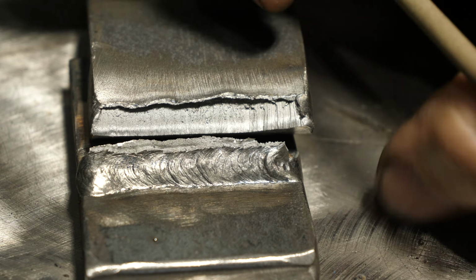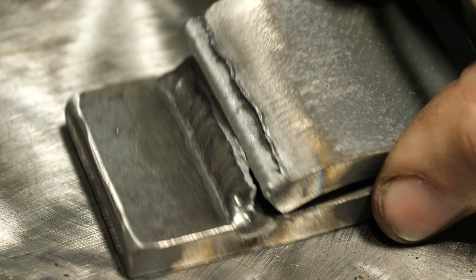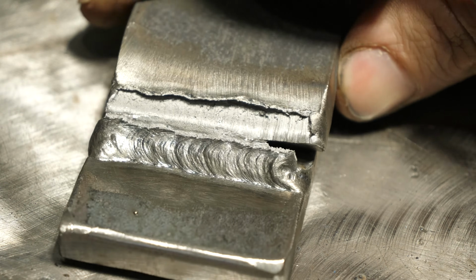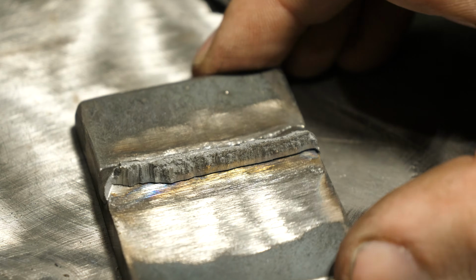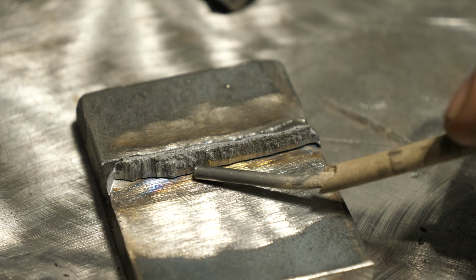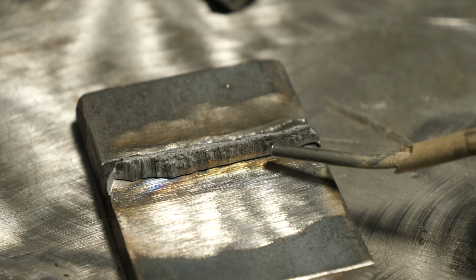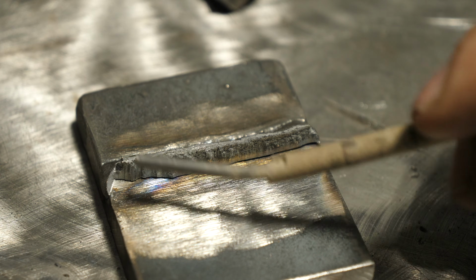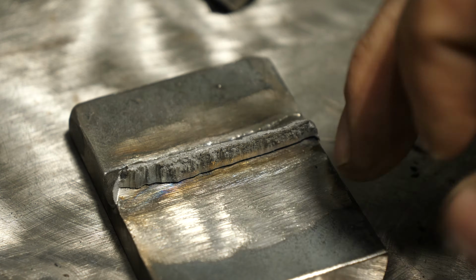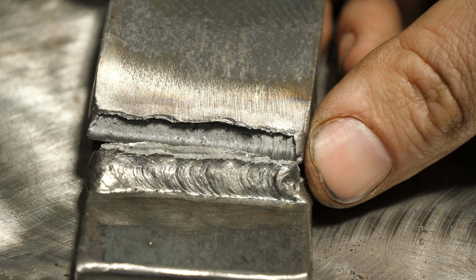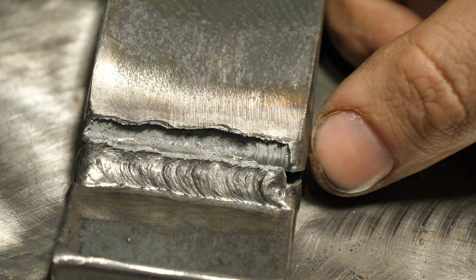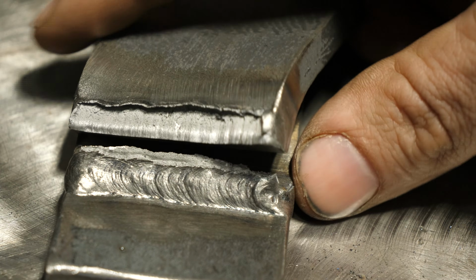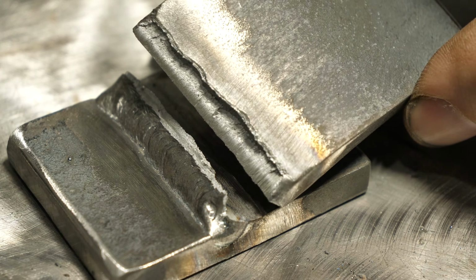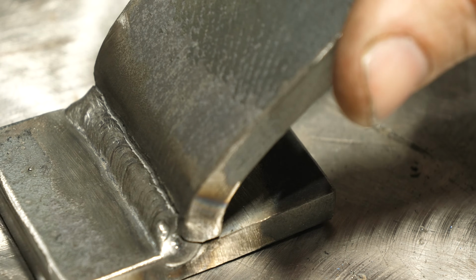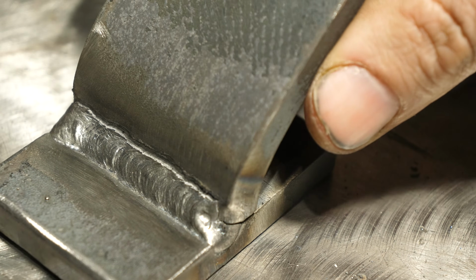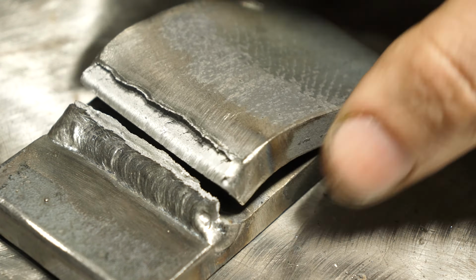So the interesting thing on this one is it actually appears to have torn the plate clean off the weld. And if you look at the backside of this weld, you can see that whole line there's like a gap under there. That's because the plate tore off, and you're not seeing the weld that fused that. The plate failed. All of these welds that I've been doing in this testing series have been cut off the same bar stock, so I don't think it's like, oh, this had a weaker piece of bar stock, because they're all the same piece.